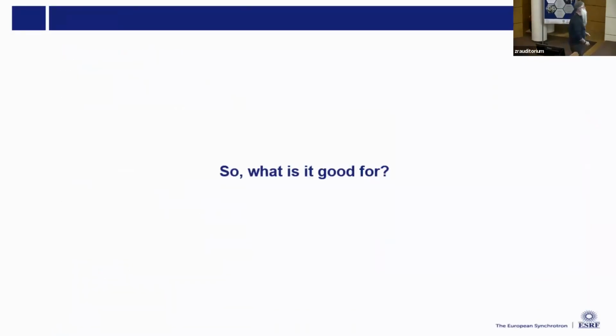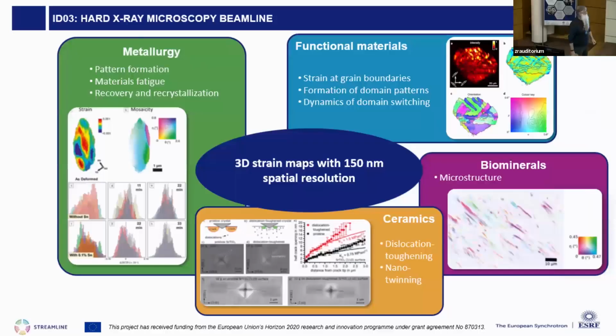So what is the technique good for? This may look a bit familiar, the format. Our main field of application right now is metallurgy. We have a relatively large community of users that look at metals, plastic deformation of metals, recovery, meaning that when you have a deformed metal, you start to anneal it, and then defects start to move around, to disappear, the crystal quality becomes better, grains grow, recrystallization occurs. That is a very large percentage of our users right now.